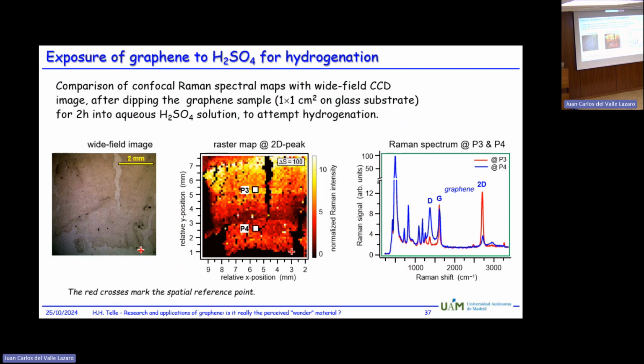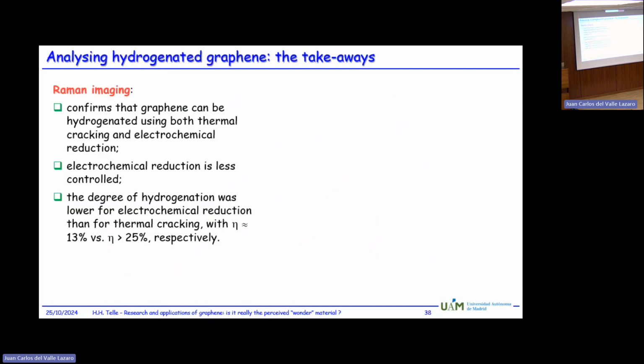So basically, the takeaway from this brief study is that it is possible that you can hydrogenate graphene, but that basically the wet and simple approach is certainly not as good as the one where you do thermal cracking in the system. But nevertheless, you could produce reasonable hydrogenation of samples. With the thermal cracking, you can generate about 25% of coverage.